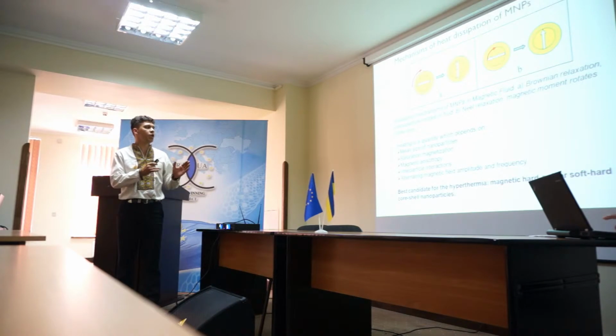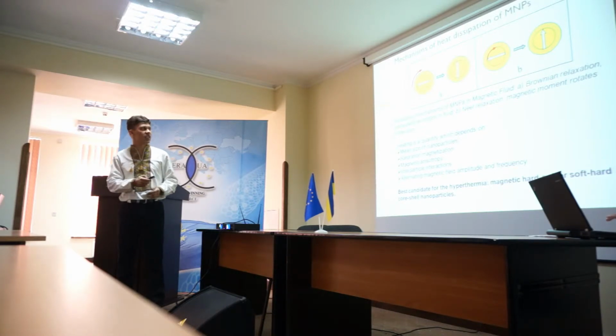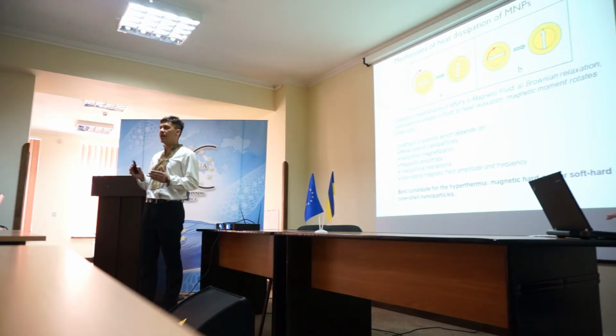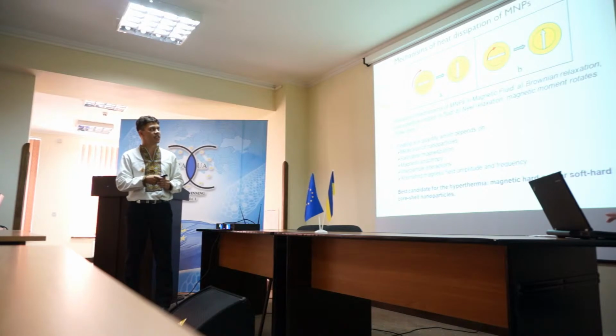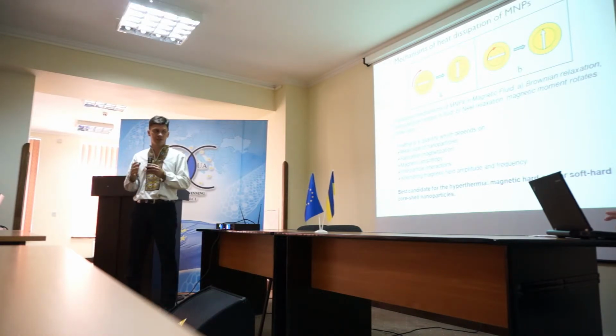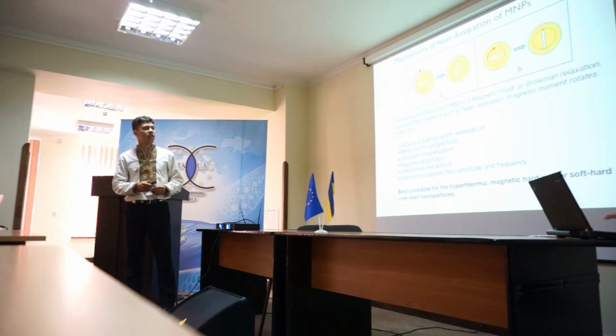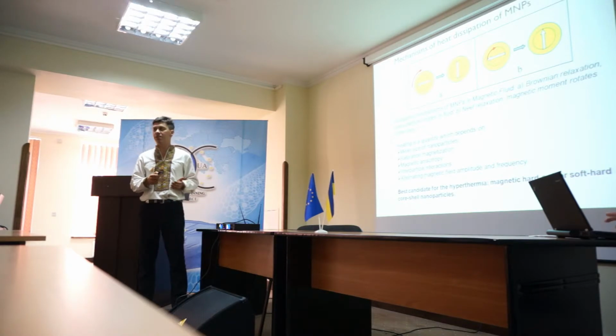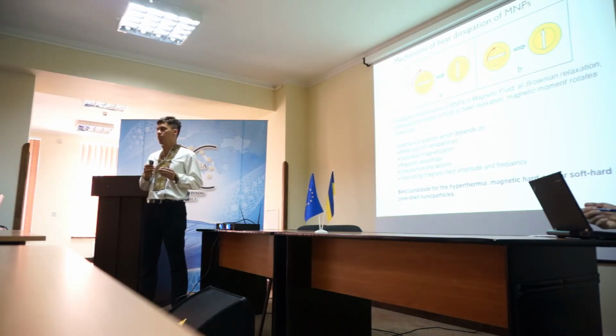The heating of nanoparticles occurs when the magnetic moment of the nanoparticles rotates, and we have two possible relaxation mechanisms in superparamagnetic nanoparticles. It's Brown relaxation, when the whole nanoparticle rotates in the fluid, but the magnetic moment in the nanoparticle is fixed along the crystal axis. The heating of nanoparticles is due to shear with the fluid. And when the magnetic moment of the nanoparticle rotates but the nanoparticle itself is fixed, it means that the nanoparticles undergo Néel relaxation. In this situation, the thermal energy is dissipated by the rearrangement of the atomic dipolar moment within the crystals.